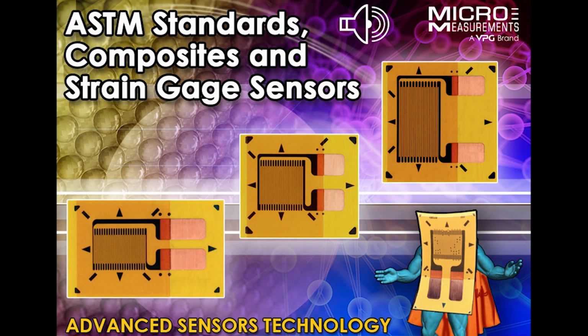So depending where you pick your modulus with a crosshead displacement, you could be off easily by 50% in some cases. Wow. So depending on the fiber orientation and all that, it's very critical to use a strain gauge for those tests. And you'll see a lot of labs or companies report only compressive strength. The reason is you have to add a gauge to get the modulus, and if you don't want to report the modulus, you're only going to see strength.